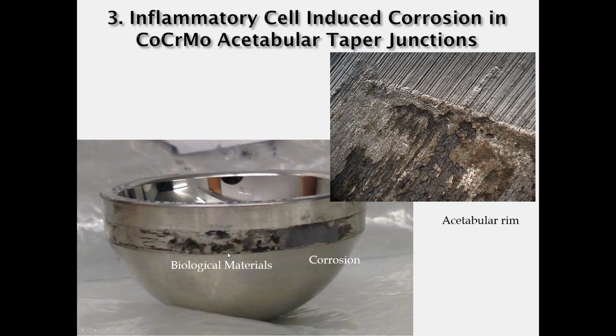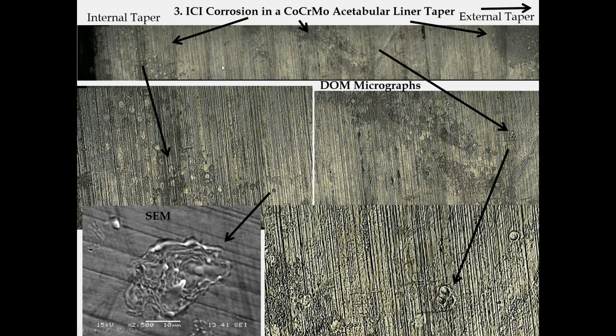And I'll just show an example here, where in digital optical microscopy, we see this very low magnification montage that's been magnified in this region to show these features, and then magnified again to show this is a cell-induced corrosion process. Similarly, in the mid region of this modular junction, if you zoom in, you see those 3 dots there, and then zoom in a little bit more, you see those. That's a characteristic pattern of cell-induced corrosion as well.